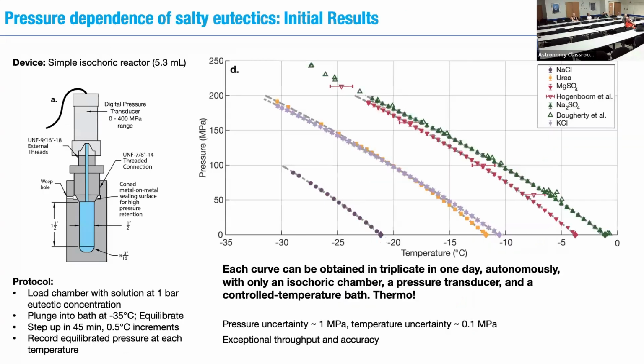So our initial trials doing this were really exciting. We took a number of salt systems of interest to icy worlds, and we just went and measured the pressure dependence of their eutectics over 20 or 30 degrees. And you can see here that for the scant literature data that was available, the results we got agreed really well. And something I want to point out here is that with this technique, because we don't have to control pressure, and because we aren't using an optical evaluation technique like a ruby technique or a fluorescence-based technique, we can get insanely repeatable and low error pressure measurement.